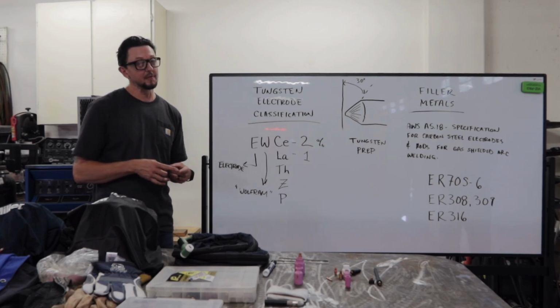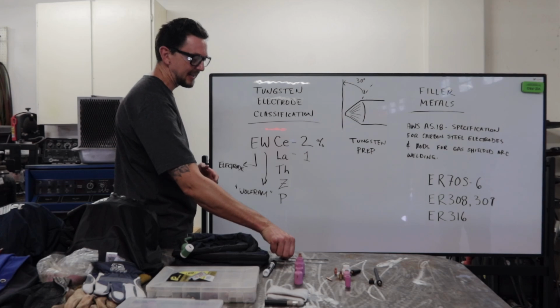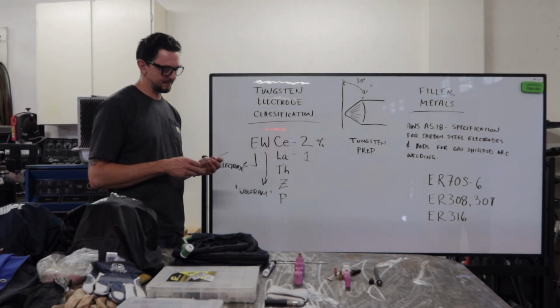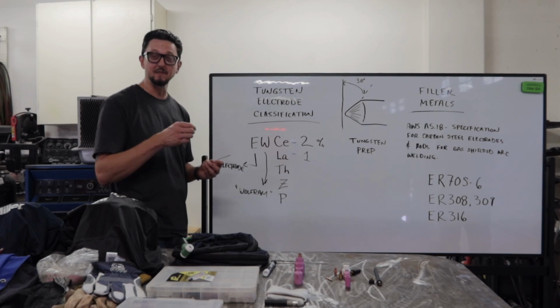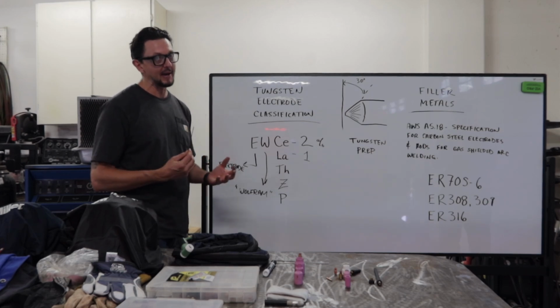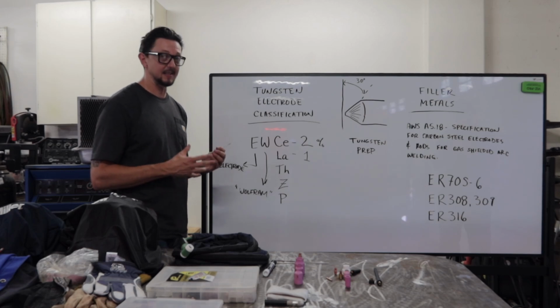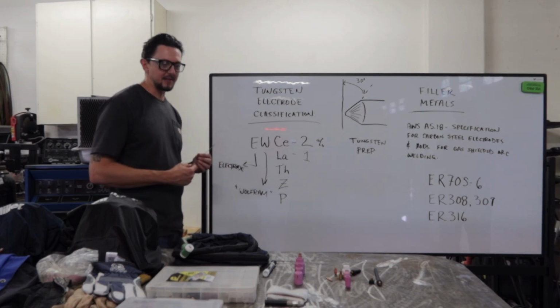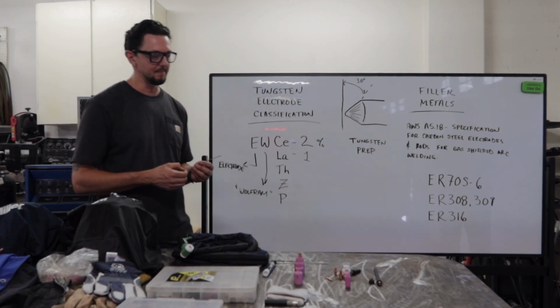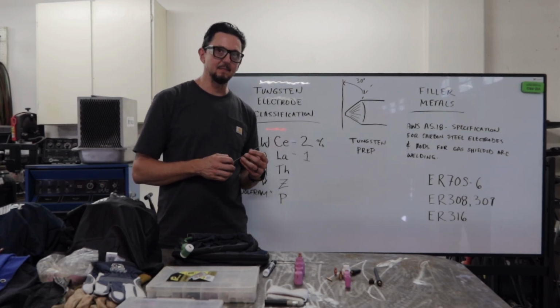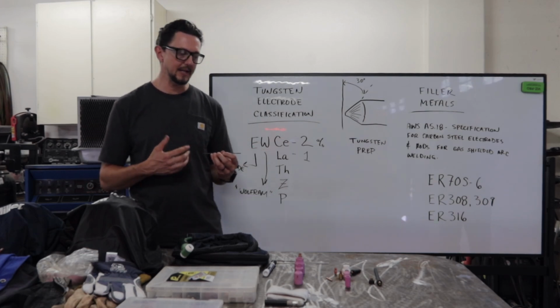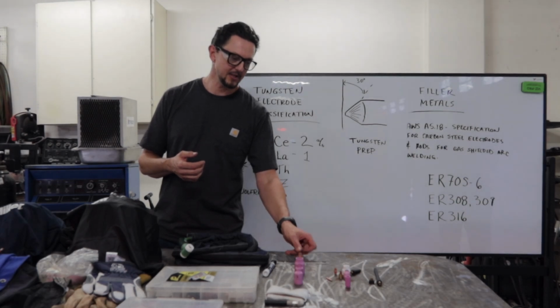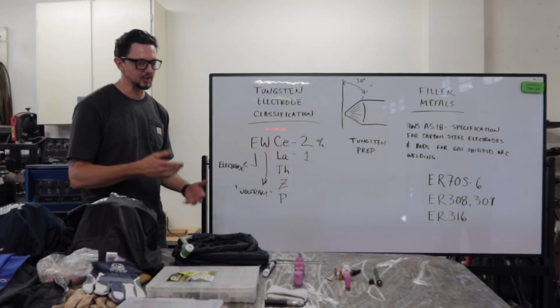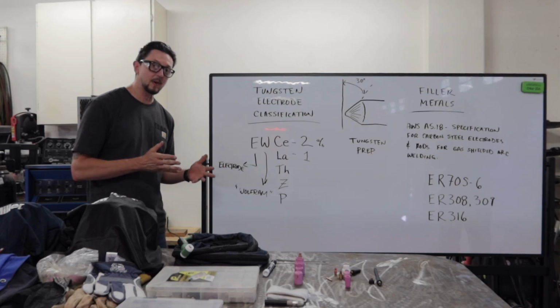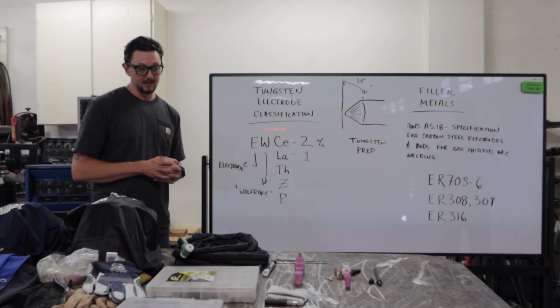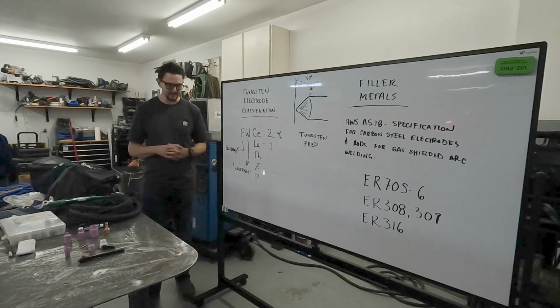They were really well performing tungsten though. They resist contamination if you dip the weld pool and that sort of thing. So back in the day, I really did like my thoriated tungstens. I still do like them, but now that there's other options, like I use trimix now, like an E3 or something like that, on carbon steel and on pipe instead of a thoriated tungsten, and they're almost just as good. So there are other options that aren't carcinogens like a thoriated tungsten. So if you see a red color band, make sure that you're taking care with that because they are radioactive.